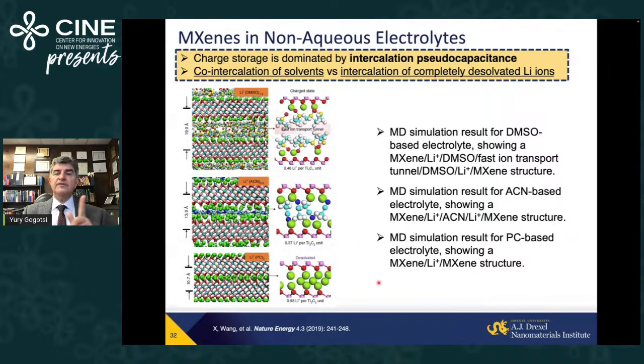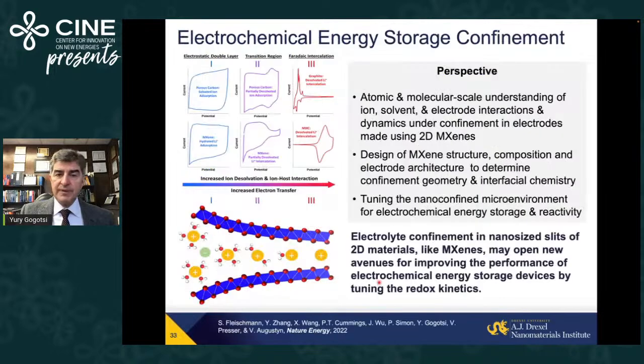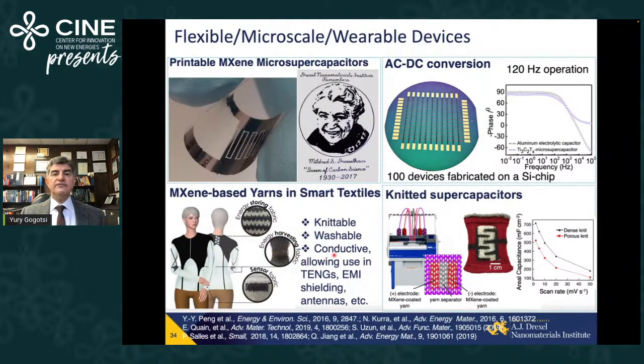So we need to find the right ions, we need to find the right solvent, we need to select from a huge number of MXenes. However, if we do it right, we should be able to get everything from double layer capacitance for very fast discharge, for example, very long cycle life, to pseudocapacitors, partial desolvation of ions, to complete desolvation and intercalation between the layers of naked ions. I'm not going to give you recipes for how to design an energy storage device. What I want to show you is that this new family of materials allows you to pretty much select and tune for application requirements. And of course, whenever you work with low dimensional 2D materials, you also can take advantage of geometries that conventional materials cannot give you.